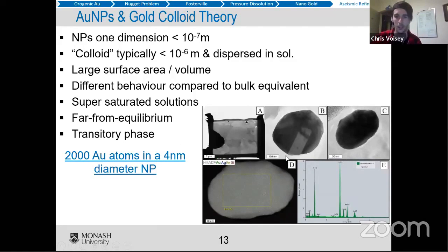So these are some nanoparticles that I took from Fosterville. These live inside a quartz vein. This is just a little analysis to show that it's made of gold. This copper peak here comes from the holder. So when you do these analyses, it's put on a little copper grid. So ignore this thing. This particle is pretty much all gold and maybe a little bit of silver.